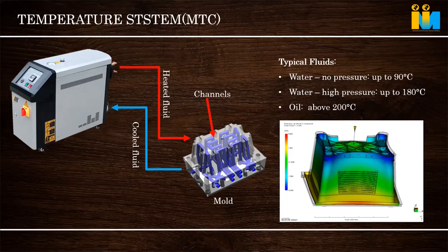That's why whenever we are using a raw material which has a higher mold temperature requirement, we have to go for a mold temperature controller. Its purpose is to heat the oil or whatever and send it to the mold. Generally oil is used because it will not boil at 120 or become fume. Some temperature controllers use high pressure water: when we exert pressure on the water, its boiling temperature goes up. Those are known as high pressure water temperature controllers. Very effective, but costly, because the water has to be compressed and kept at a higher pressure.